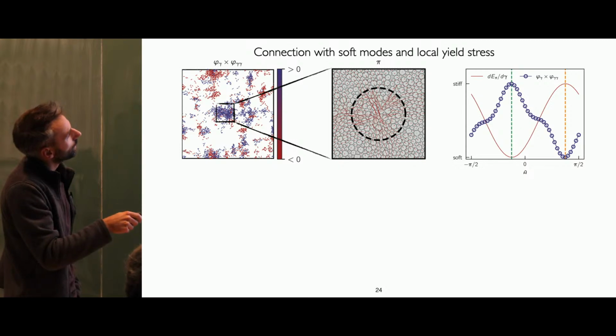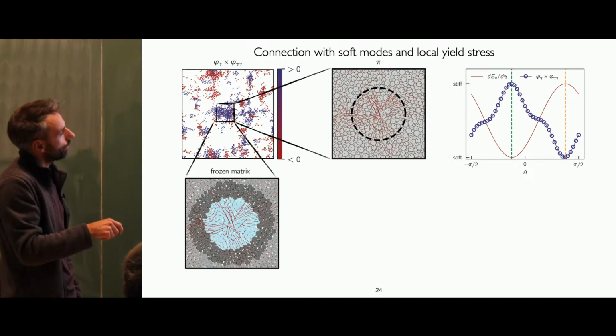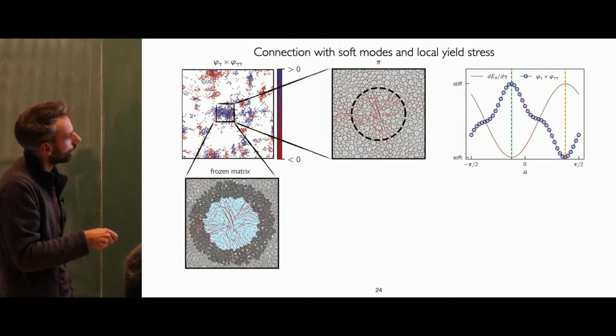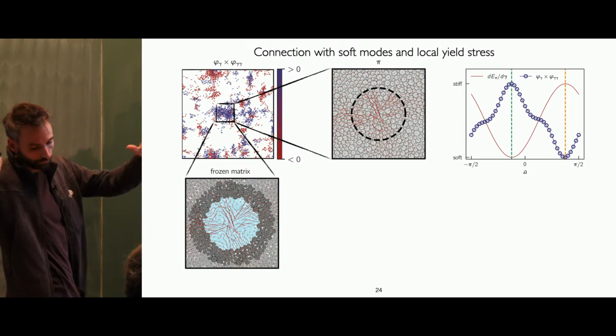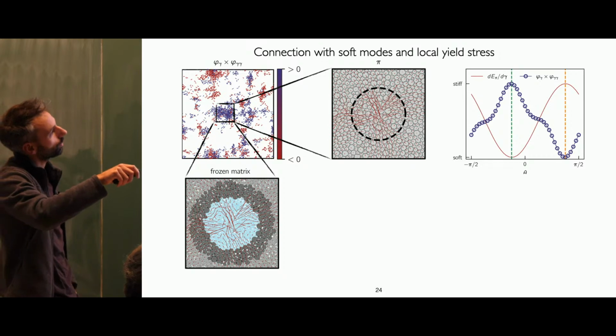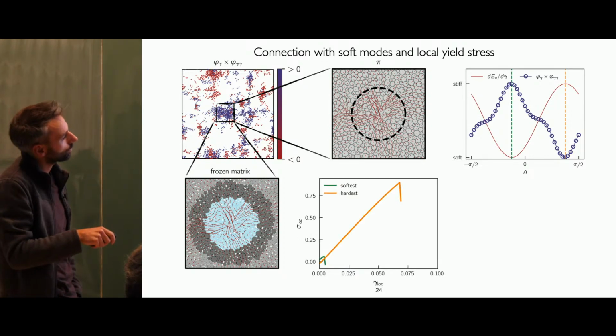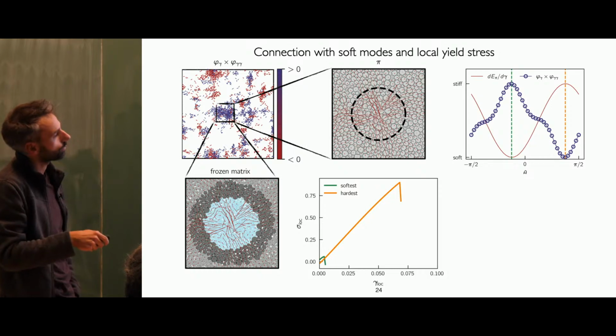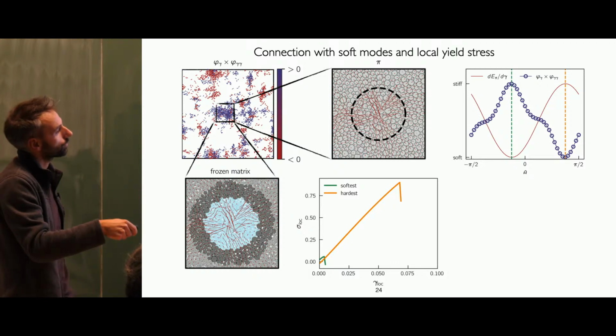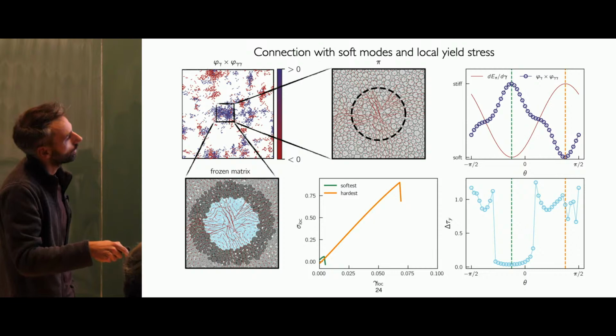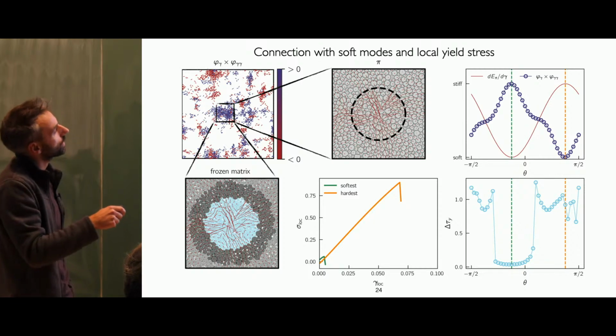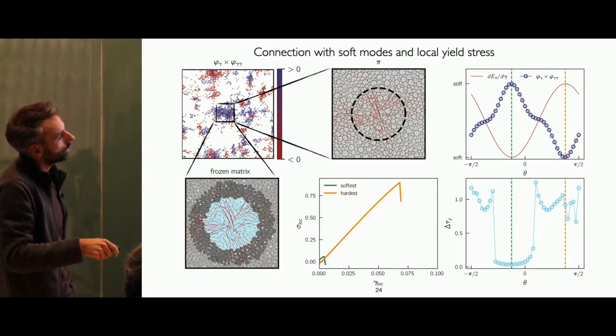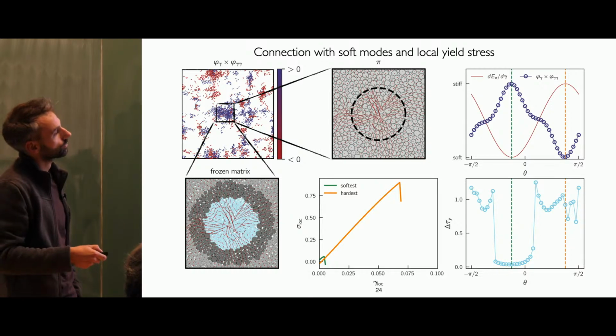Then you can take the same patch here and now put a cavity around and do the local yield stress. I can now take my blob, freeze my matrix, and then shear it in, for example, the green and orange direction. And this is what you will see. In the least favored direction, you can undergo large deformation before you yield. And in the most favored, you will directly yield for a small deformation. And you can do this for any shear angle. And indeed, you see for this case, for these guys that couple well with a positive simple shear, you have a basin of small local yield stress.